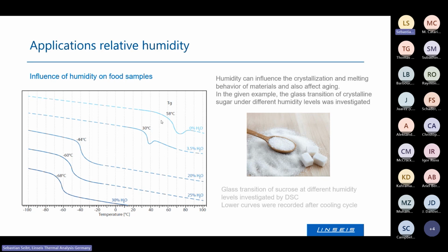And the melting point with higher humidity levels, even if it's only 3 or 4%, already shifted the melting from 60 degrees to around 30 degrees.